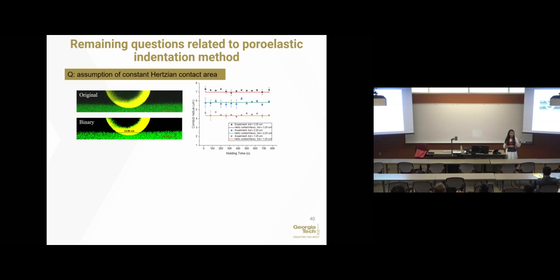So at the end, this is the last slide. I want to draw your attention that at this point, I have shown that the indentation method works. But an often question that I get from the audience is, what about the adhesion between the indenter and the gel? And we have always argued that it's negligible. Only until recently, we have an integrated AFM and confocal. So while we measure this force and apply displacement, we can visualize how the material deforms at the same time.